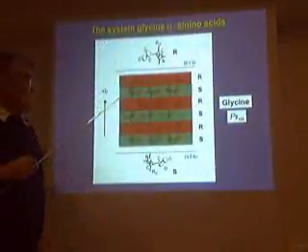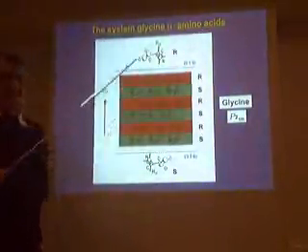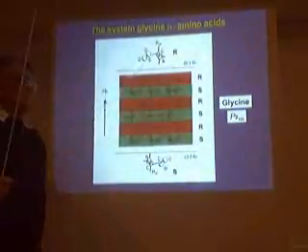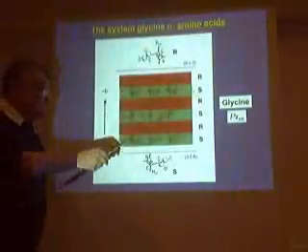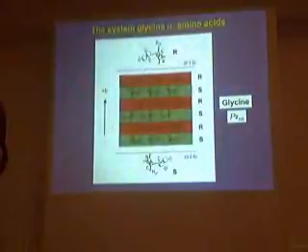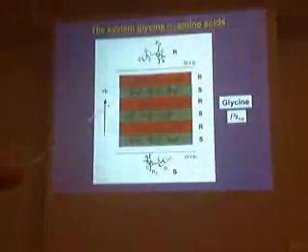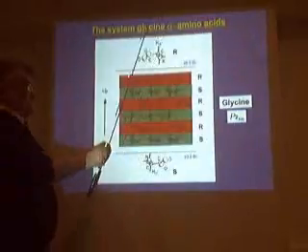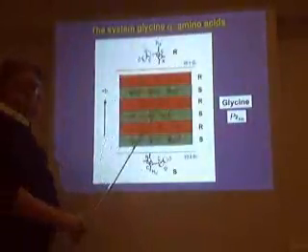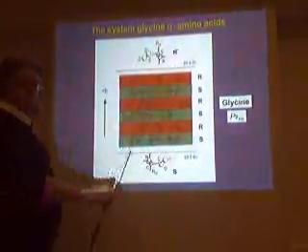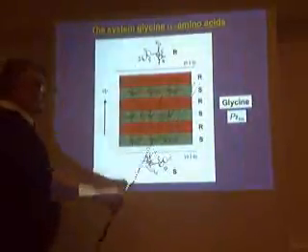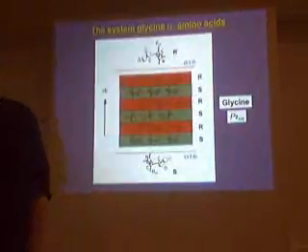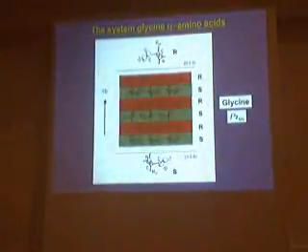Okay. Now, if you take the next layer of glycine, it is related to the first layer by a center of inversion. Okay, and therefore it has exactly the opposite handedness as the first glycine. If you go to the third layer, you can see again it is related by a two-fold screw axis. They rotate and then move. And then you go to the first one and you build the unit cell. Okay? So you have layers of R and layers of S, layers of R, layers of S, and so on. So what now happened? We spoke about reduction in symmetry.